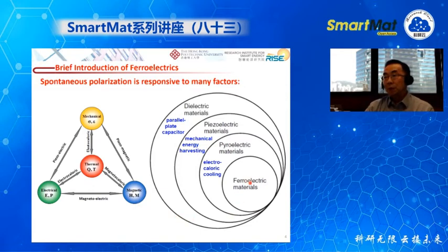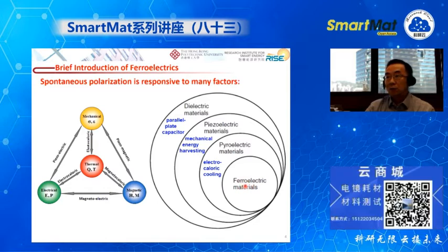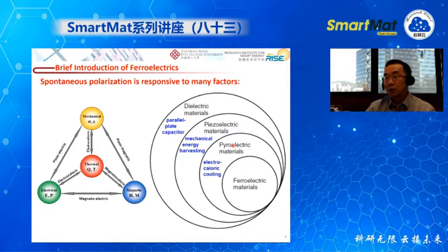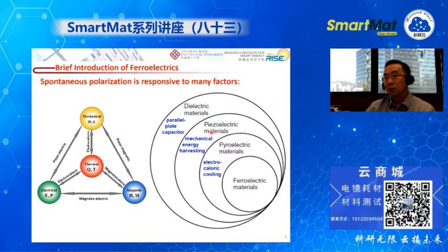The ferroelectric material actually belongs to a group of the pyroelectric material. Here, pyroelectric means when you change the temperature of the material, the polarization will be changed. And it also belongs to an even larger group of the piezoelectric material. Piezoelectric material is a kind of material when you apply a stress or strain, you generate a charge on both surfaces of the material. And all the ferroelectric, pyroelectric, and piezoelectric materials belong to an even larger group of materials, that is the dielectric material.